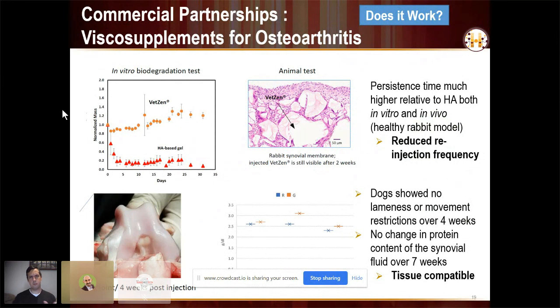You see that the gel does break apart, which we didn't anticipate, honestly, but we think could actually be another benefit because now these particles can also move past each other, and it might actually help with lubrication even more. And we don't see the inflammation that might be the red flag with that approach. We've also had this in a dog joint, and you see no inflammation or problematic morphology 4 weeks post-injection, nor is there any change in the protein content in the synovial fluid.